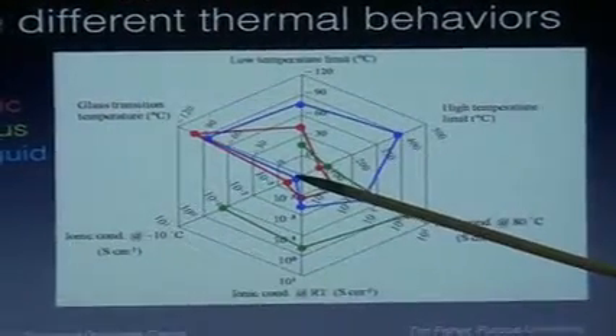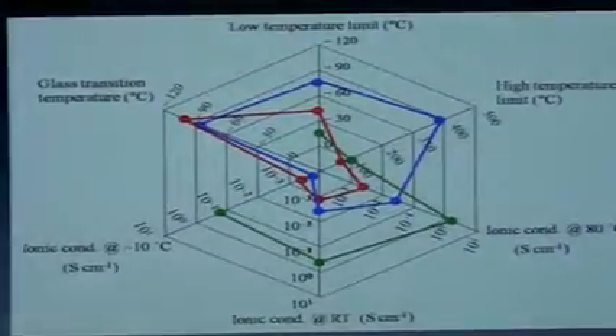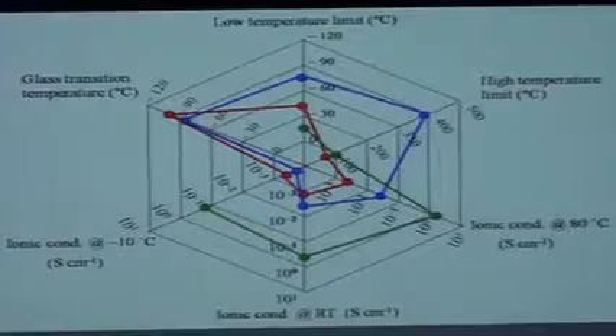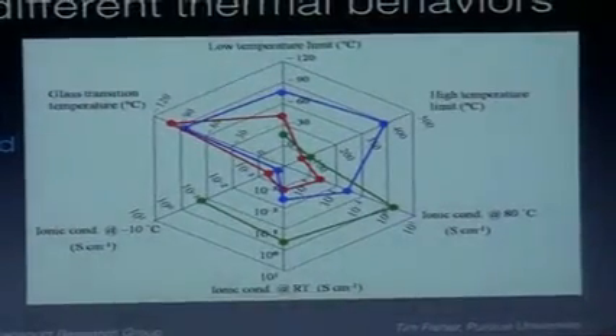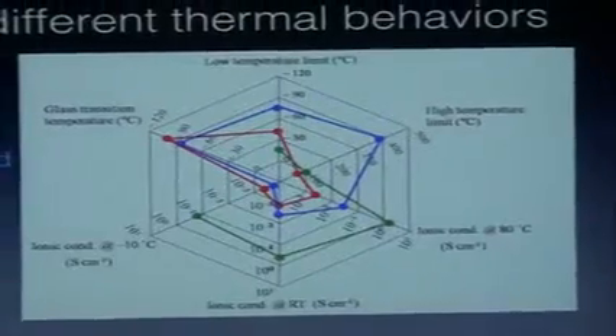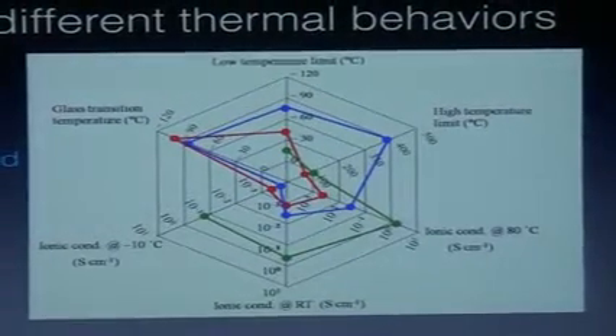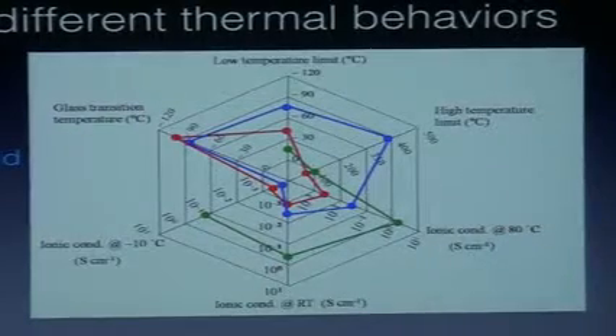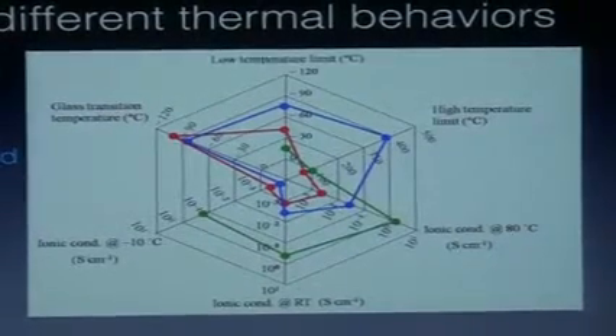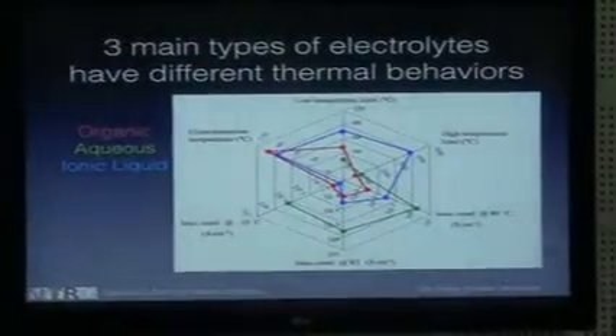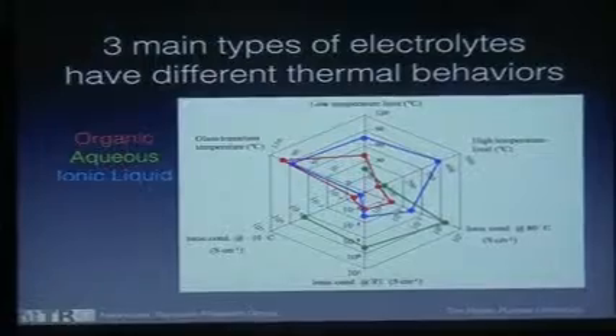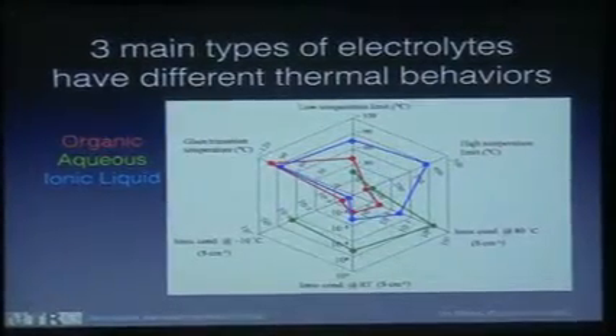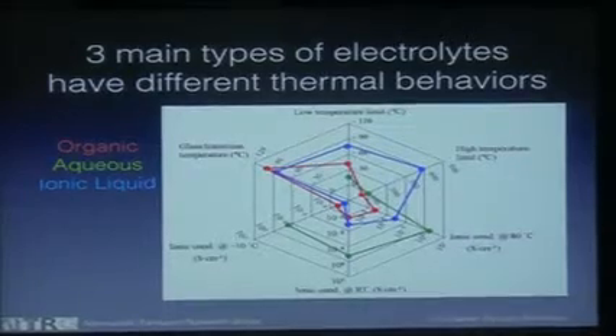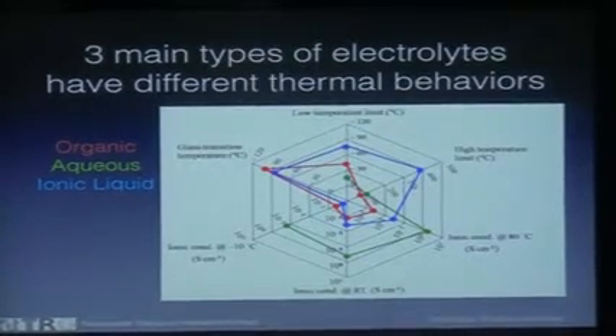You see the ionic conductivity, this blue point, that's the ionic liquid, is almost in the center of the chart at very low temperatures. So the conductivity of ionic liquids is highly temperature dependent. That's going to affect your series resistance, which will have an influence on overall performance. Aqueous electrolytes, on the other hand, look pretty good in this context, especially for conductivity, right? The problem is that they have a high low temperature limit. So it's just near freezing that is going to be the low temperature limit. And that's not low enough for many applications, at least for general products, right?